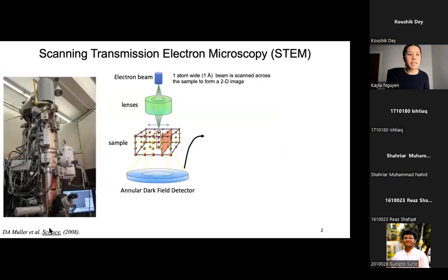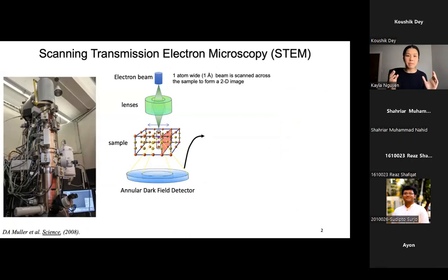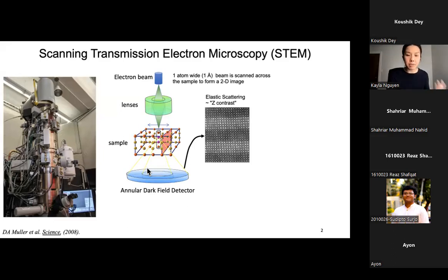All right, cool. So the technique that I utilize in my research is called scanning transmission electron microscopy, STEM for short. What happens in a scanning transmission electron microscope is you have an electron beam that gets focused down to a spot that's about an angstrom wide with electromagnetic lenses. You take your electron beam and you scan it across the sample. At each scan position, the scattered electrons get collected into this annular dark field detector. And you can integrate that signal up to form really nice atomic resolution images.